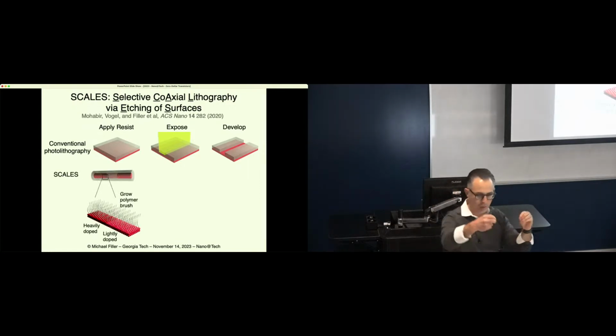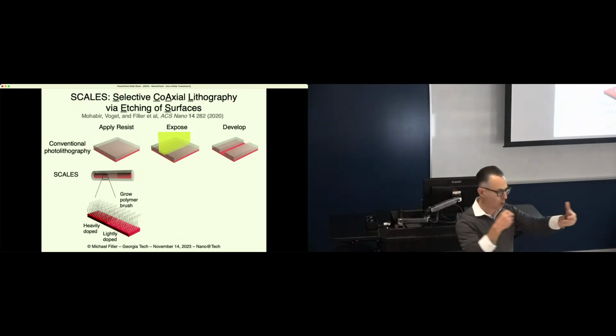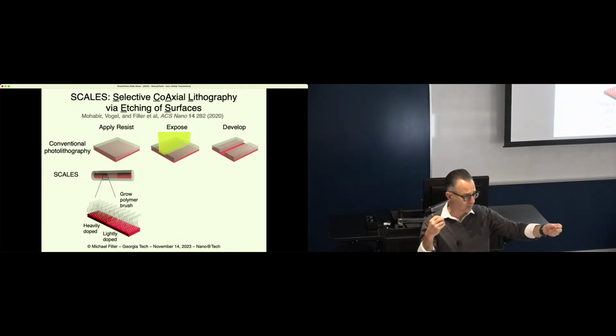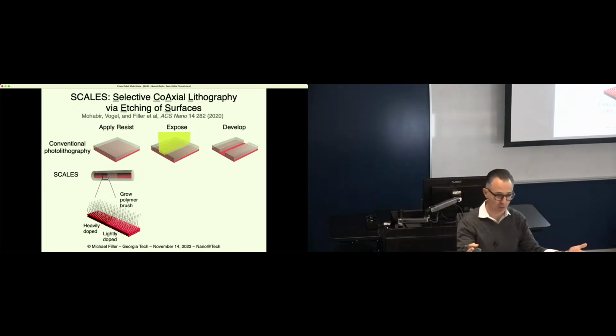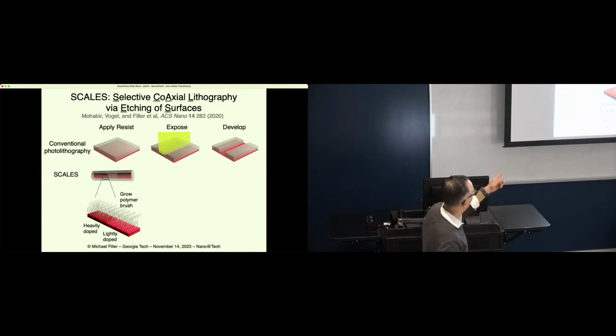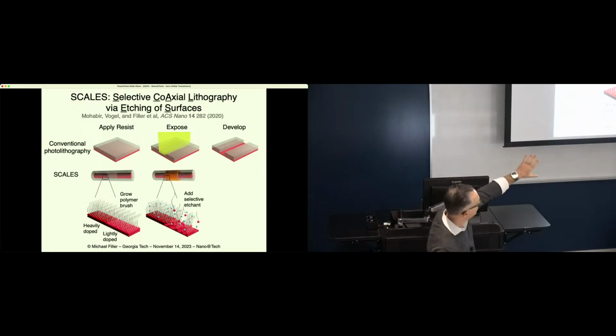So we're going to do something similar where we take our nanowire that we've grown with source channel and drain, and we're going to grow off of that surface a polymer. It'll be everywhere, a lot like when you spin a resist on a wafer. The polymer will be everywhere on the nanowire. And then instead of using light, we use chemistry. So we apply a selective etchant.